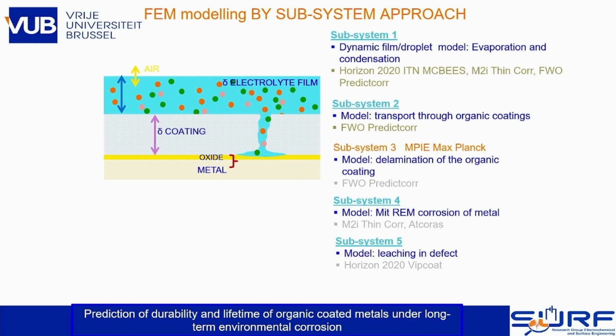Then we have tried to come up with a finite element model for the delamination that we are doing together with the Max Planck Institute in Düsseldorf. I must say that at the moment we are not successful, and the reason is that the Max Planck is revising the theory of the delamination front side. They come up with another theory which leads to a modification of the equations in the finite element model. Then this is the corrosion model, and the last one is the leaching model of an inhibitor in a defect.